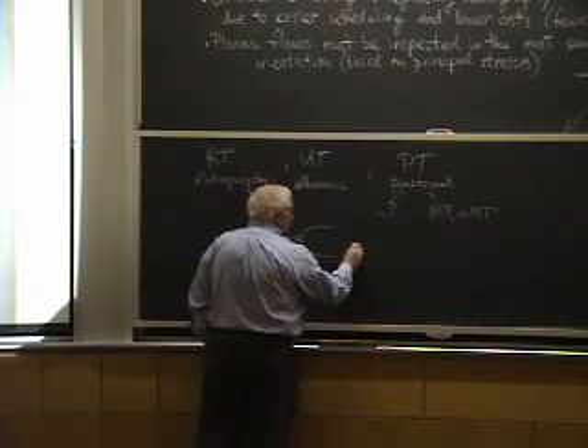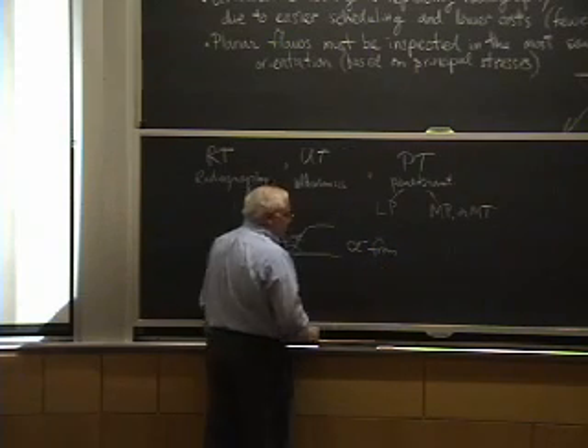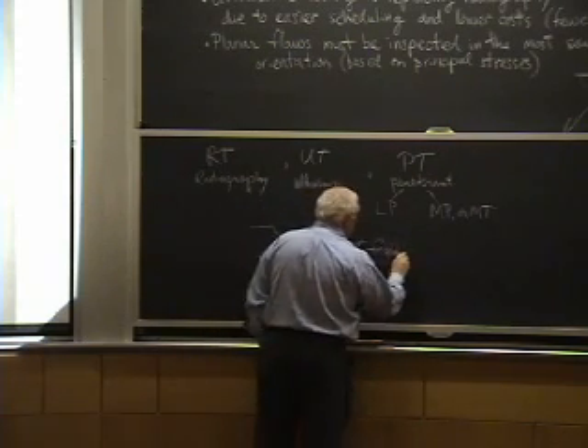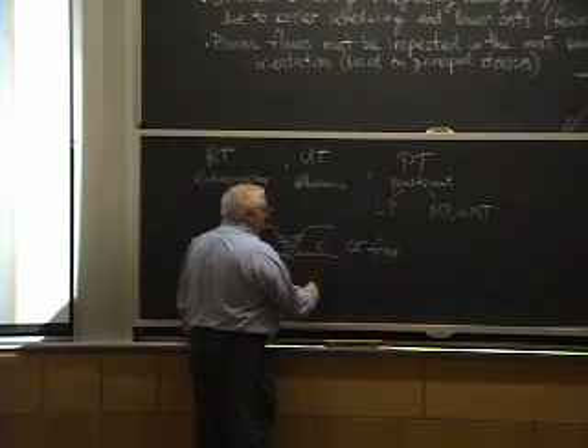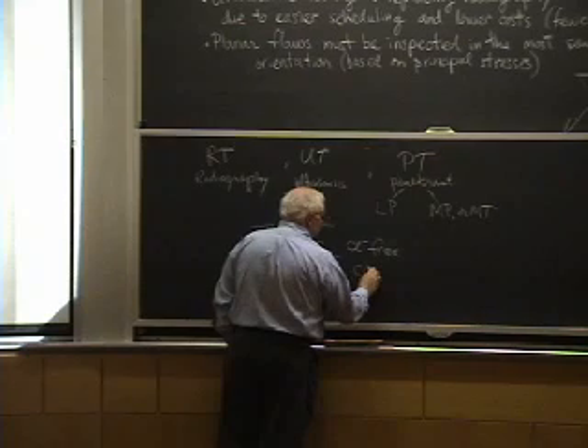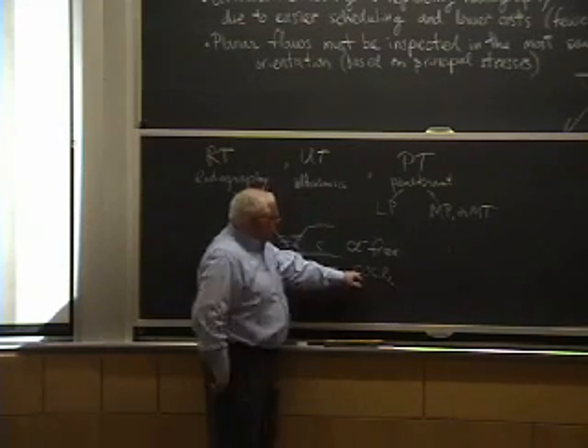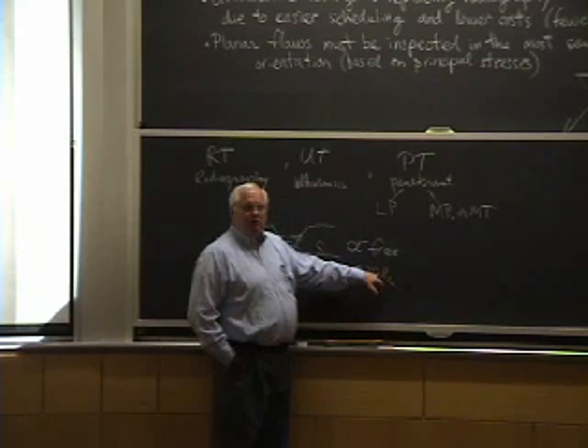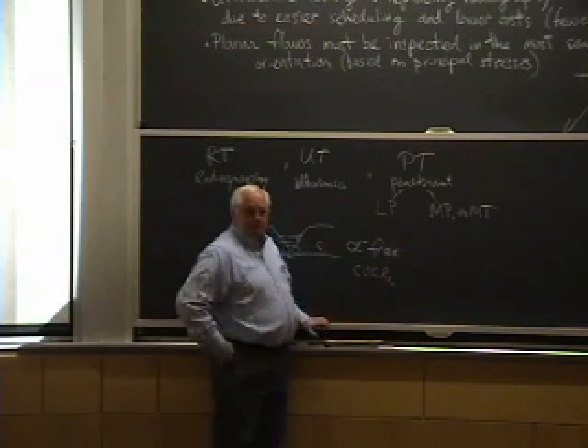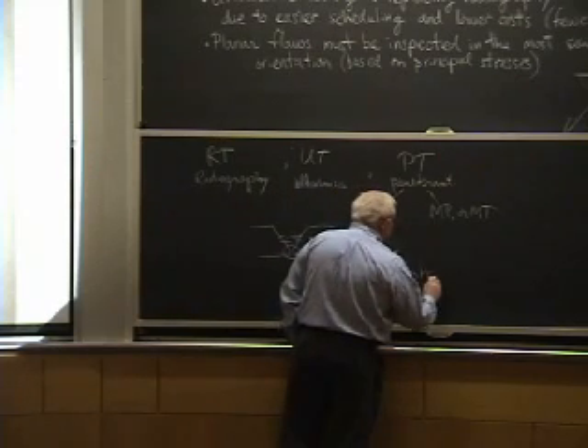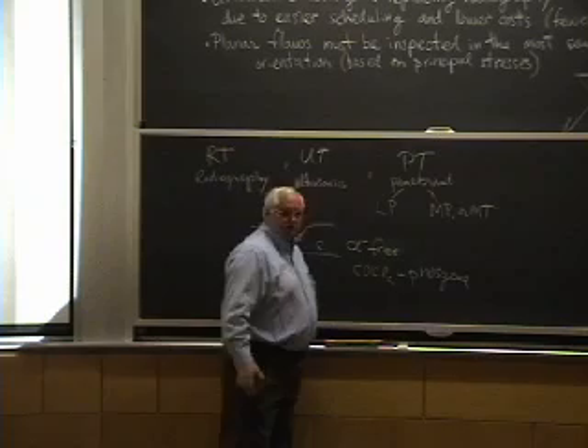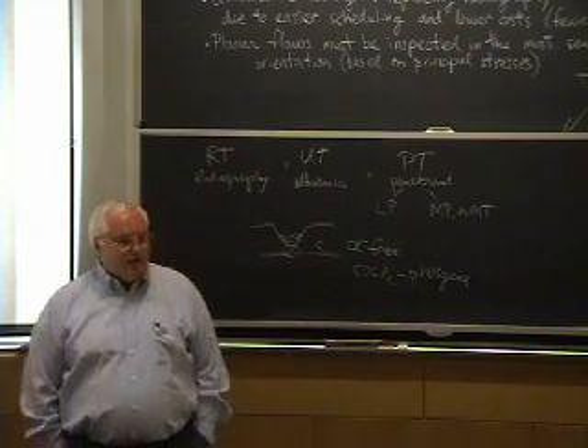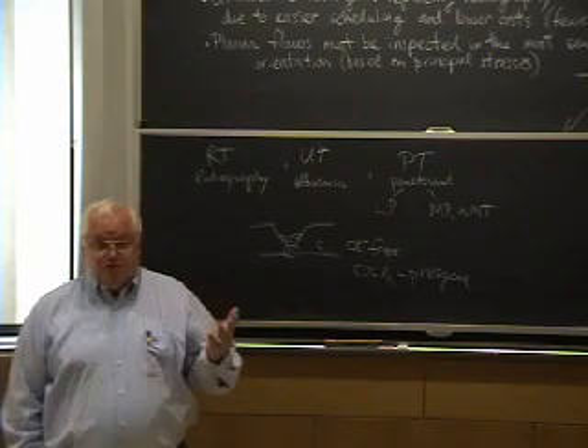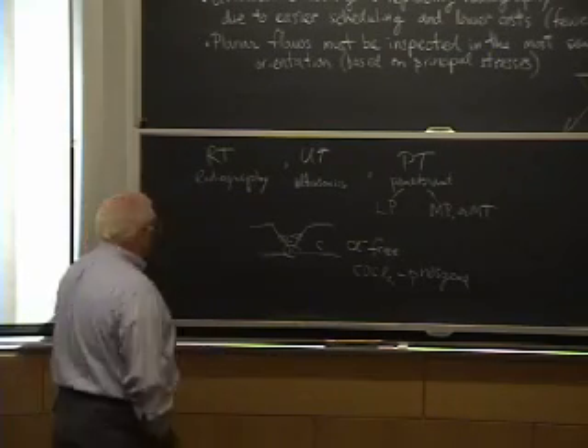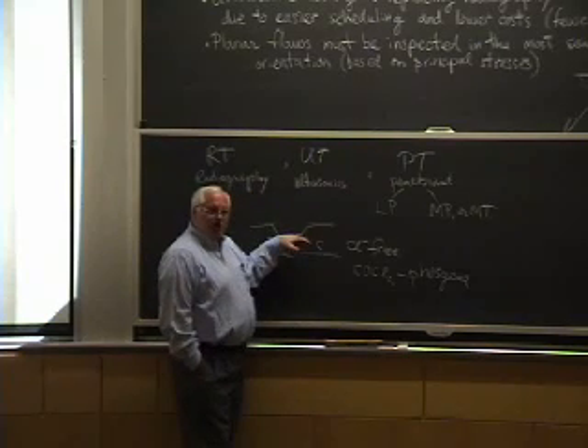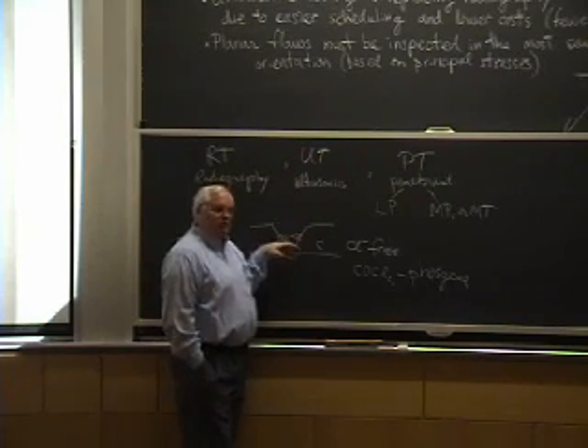So you like to have things that are chlorine-free. If you're doing steel, the reason you want chlorine-free is because steel has got carbon in it, and oxygen is in the air. If you have chlorine present in the plasma, you will form a compound of carbon, oxygen, chlorine. Anybody know what that's called? It's called phosgene. Anybody know what phosgene gas is? It's one of the gases they used to gas people in World War I. Okay, it's a very toxic gas, and it's a fairly simple gas. But if you have in your liquid penetrant materials a material that has chlorine in it, you can have problems. On some of your stainless steels, the chlorides can create problems.